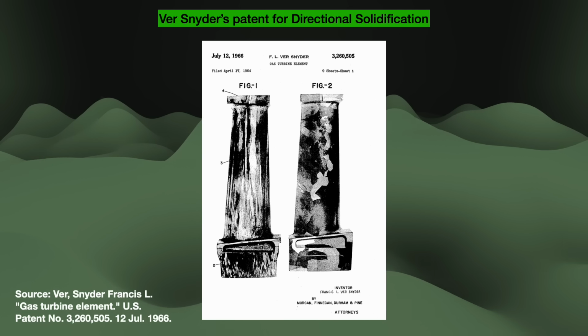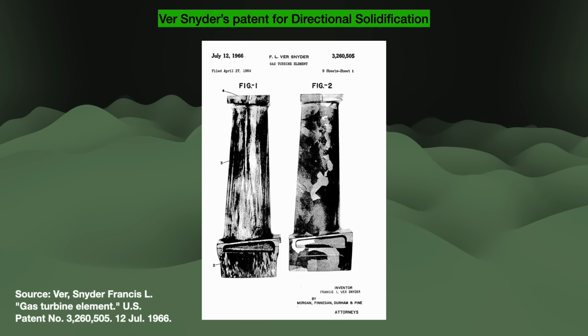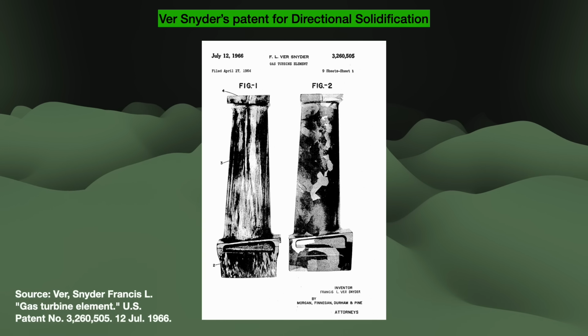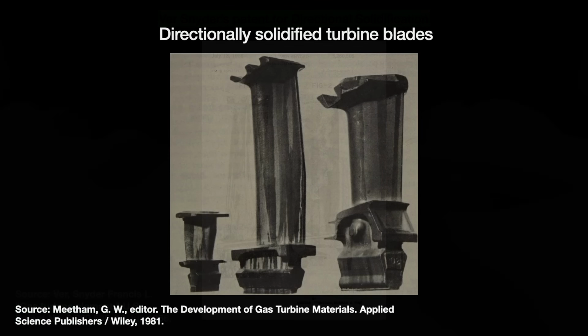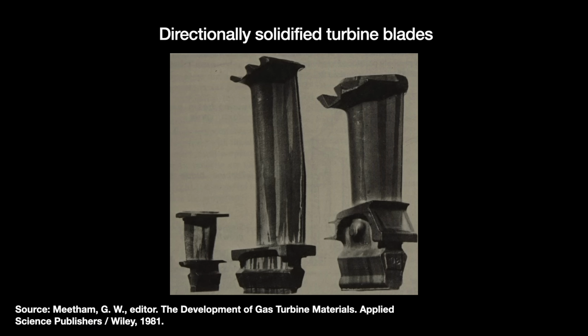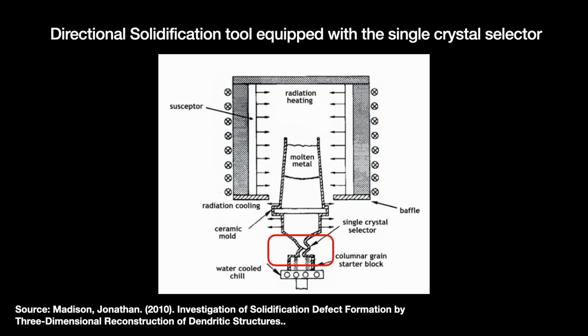After this, the obvious next step is to eliminate the grain boundaries entirely and make the whole blade a single crystal. The techniques to produce these were pioneered at the same Pratt & Whitney research lab team that commercialized directional solidification, led by a brilliant scientist named Frank Versnyder. While experimenting with the casting molds, they noticed that adding a right angle bend to the starter chamber mold above the bottom chill plate filtered out some of the vertically growing columnar crystals by blocking their growth paths. They discovered that adding more bends led to fewer crystals emerging over those bends. The team later swapped out the right angles with a smoothly curving helix shape. In industry, this helix is referred to as the pigtail.